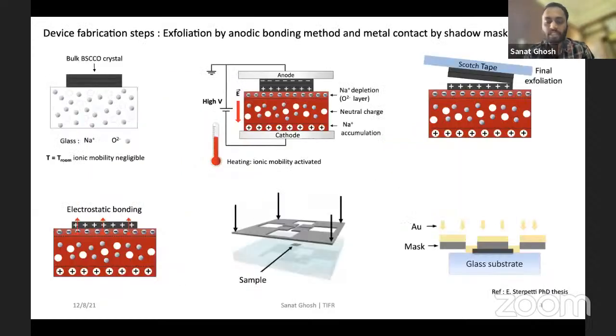Now, before going to the device result, let me briefly tell you how we make these nanowires. As I mentioned, BSCCO is a van der Waals material and can be exfoliated like we exfoliate graphene. Usually we exfoliate graphene or other 2D materials by the Scotch tape technique. Instead, here we use a different technique called the anodic bonding method. The reason for using this method is that this way we can get a large area of thin layers of BSCCO, and the procedure is as follows. As a substrate, we take a special glass substrate which has sodium ions doped in it, and we place a bulk crystal of BSCCO and heat the total assembly.